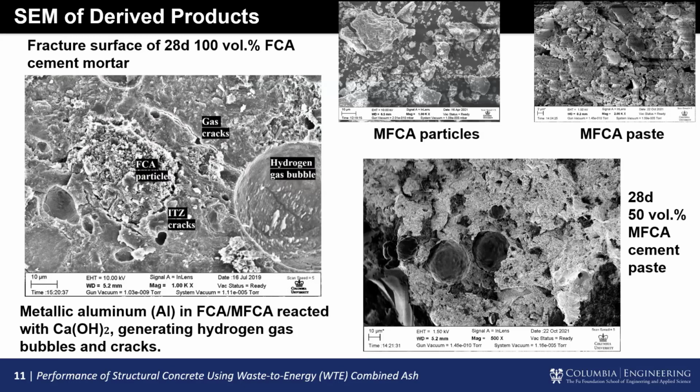And also the interfacial transition zone was generated around the ash particles. And this is the reason why, with the increasing of the fine combined ash, the compressive strength decreased, as I discussed in the previous slides.